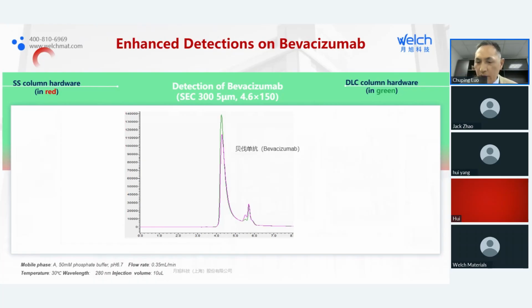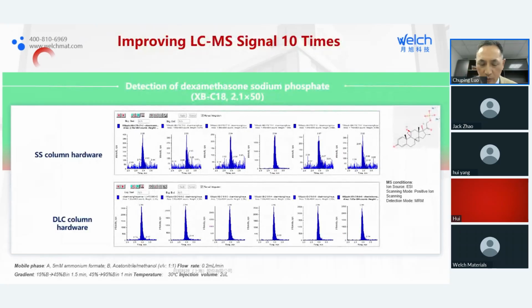This one works on the sample on the right side. You see the structure. It has one phosphorus group in this small compound. On the top row, this is data from the stainless steel column hardware. All this experiment was done using LC-MS. Compare the signal we obtained from stainless steel hardware and DLC column hardware. DLC column hardware offers almost 10 times higher intensity compared to stainless steel.